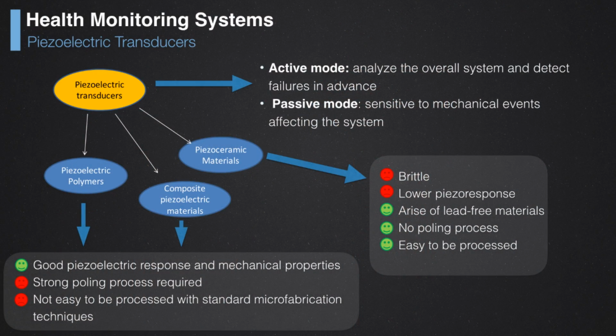There is also some issue regarding the toxicity. The most used piezoelectric ceramic material is the PZT, lead zirconate titanate, which is extremely toxic. Of course, the preparation, the fabrication process, and the technological steps that you undergo to realize a device involve the use of human personnel. Of course, it's important to preserve their health. In that case, there are certain solutions like so-called green materials, which are not toxic anymore and preserve the environment. So that's what we selected actually. Zinc oxide was the material of choice.